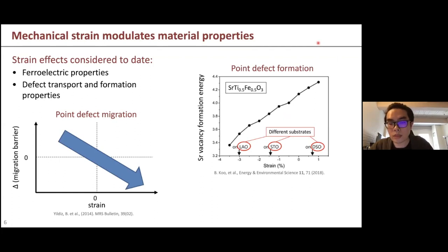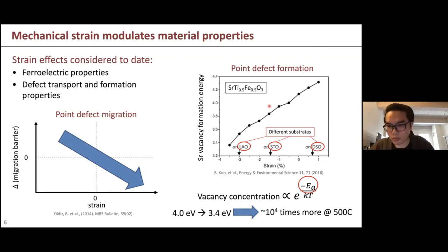So the material here, meaning the substrate that you can choose when you grow this material on it, and if you grow it epitaxially, you can create a different strain on your thin film device. The vacancy concentration is proportional to the exponential of minus formation energy over kT. When we see the term is an exponent, we see that it has a very high dependence on the temperature, and even a small change of the value can give us a very large change. To give a sense of how much it will change: around zero strain, it is around 4 eV. And if we compress it to 3%, it can go down to 3.4 eV. And then we will have 10^4 times more carriers at 500 C. So you can see strain can change the performance of the device a lot.